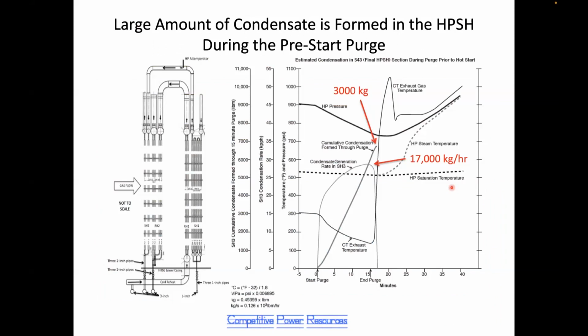So what happens in startup that causes this? This is a cartoon of a side view of a superheater and reheater. So this is the hottest superheater, the secondary superheater, gas flow this direction. This is an attemperator up here, and then here's the primary superheater back here. When the gas turbine runs at high speed to purge any combustibles from the HRSG gas path, this cool air passes through these superheater tubes. And so the superheater and the reheater become an air-cooled condenser if there's water vapor inside the tubes, which in the superheater, there is always water vapor because it's communicating with the HP steam drum.